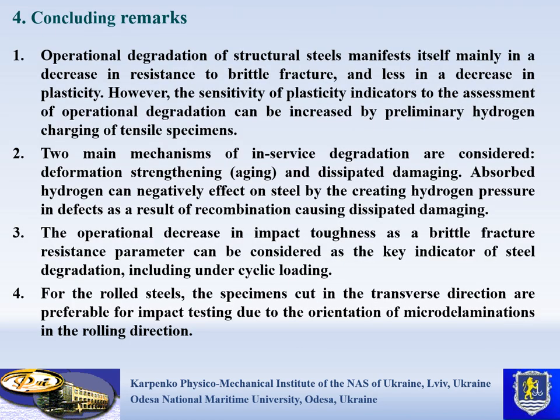And concluding remarks. Operational degradation of structural steels manifests itself mainly in a decrease in resistance to brittle fracture and less in a decrease in plasticity. However, the sensitivity of plasticity indicators to the assessment of operational degradation can be increased by preliminary hydrogen charging of tensile specimens. Two main mechanisms of in-service degradation are considered: deformation aging and dissipated damage.